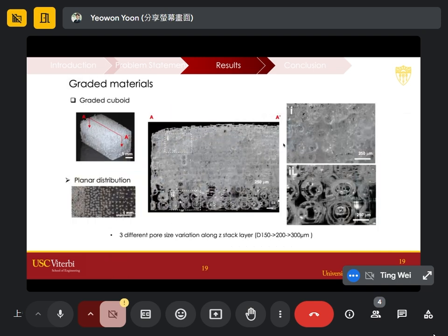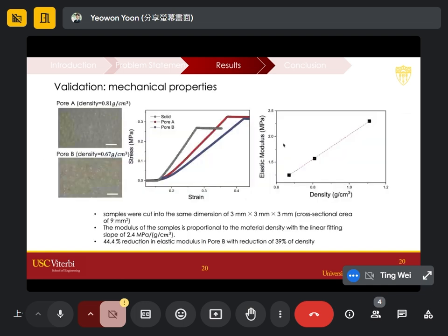Another example we wanted to show is the graded material. Graded material means that you gradually have different modulus within the same bulk material. Here you see the cuboid pattern that has relatively larger size droplets on the bottom side, and then the transition happens in two steps, where the top has a 150 micron diameter. So if you look at just one material cross-sectionally, the bottom would be relatively softer, while the top portion will be relatively stiffer. So we had to validate this using a mechanical test.